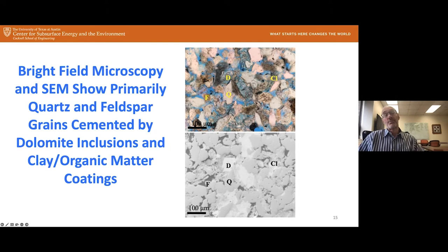So one of the first things we did, before we did experiments with it, is we wanted to just look at it up close to see if the sample we had was consistent with what was provided by the supplier of the Bandera gray. And so we used both bright field microscopy as well as scanning electron microscopy. And what you see is these pinkish type grains that are relatively smooth are quartz. When we have mottled kind of grains, that's the feldspar. The dolomite's really hard to see with the bright field. It shows up blue, almost like a pore space in these images, but in the SEM, it shows up a lot more clearly. And then we get this more thin crystal or needle-like appearance, and you can't see it in this image, but of chlorite.